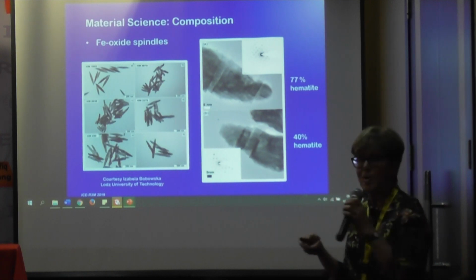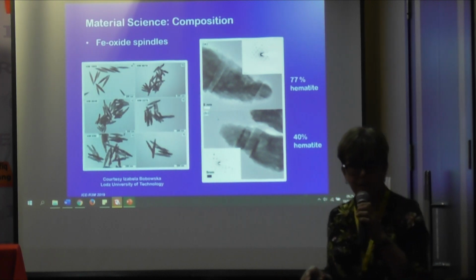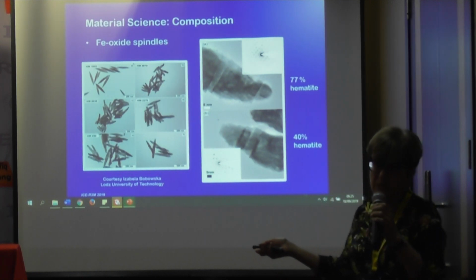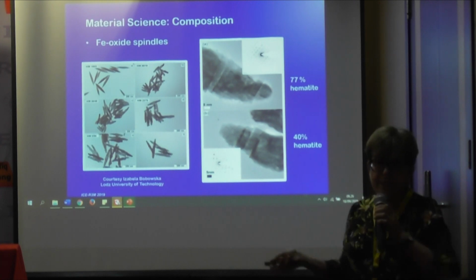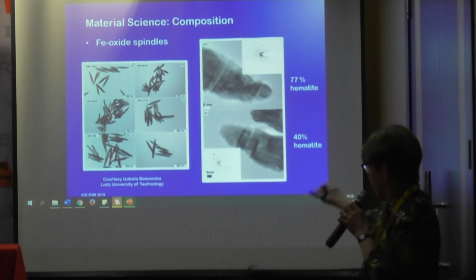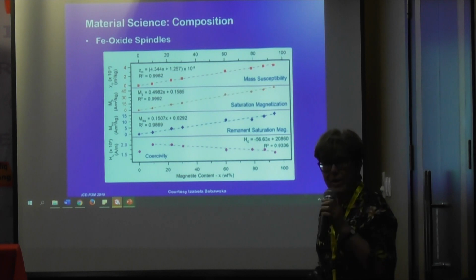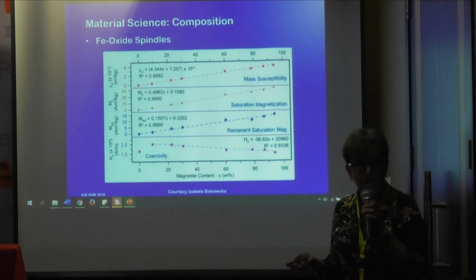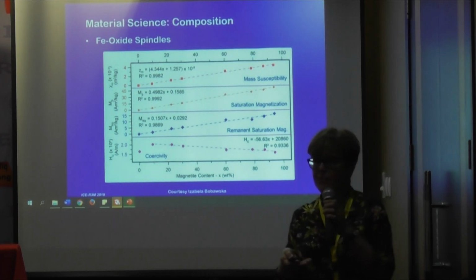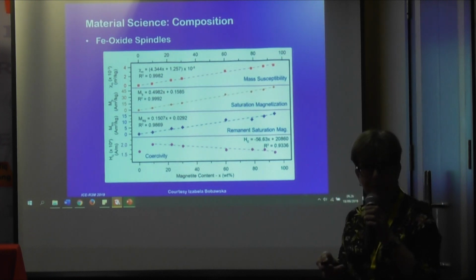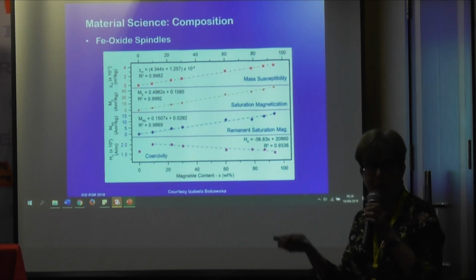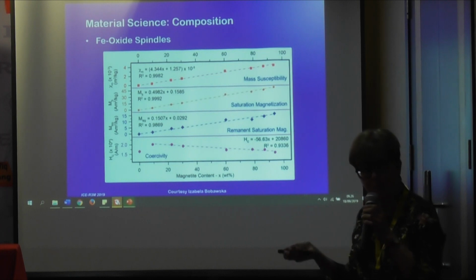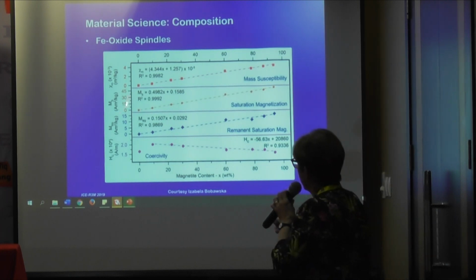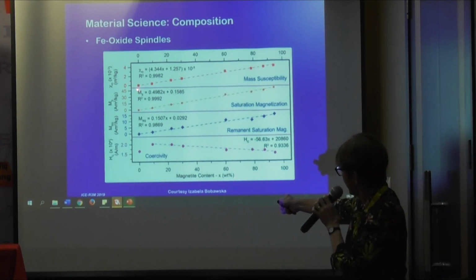And they wanted to know how successful their conversion was. Because, you know, to do TEM pictures, that takes a lot of time. So next. So we said, well, why don't we try some magnetic parameters to see how good? Because we know hematite has a very low susceptibility, low magnetization, and magnetite, maghemite, has a high susceptibility, high magnetization. And sure enough, you can see here is the susceptibility.